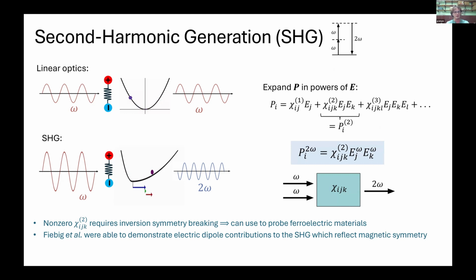Second harmonic generation is the simplest of these effects. So you absorb 2 photons, you emit a photon at twice the energy. And the reason this is such a useful characterization technique is it gives you access to a third-rank polar tensor, which is very sensitive to inversion symmetry breaking. So people have been using this for a while to characterize ferroelectric materials because you need to break this inversion center to have ferroelectricity. And it is mechanically much simpler than something with XRD, so it's easier to do in situ and look for phase transitions and things like that.